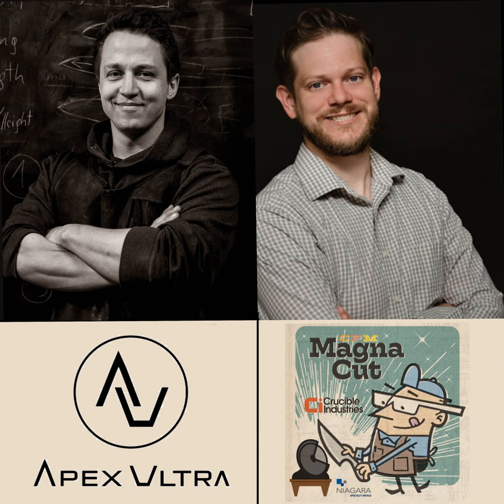I've never had any sticking issues unless with MagnaCut, because the temperature is so high that I might have used the wrong foil. So the foil was rated to 1,200 degrees Celsius, and that was too close for MagnaCut. So the foil was all soft, and this was the only time the foil stuck to the blade. Interesting. Yeah, the foil is rated to 1,200 degrees, I believe. And MagnaCut, you need like 1,100. I think it was 1,150 degrees Celsius.